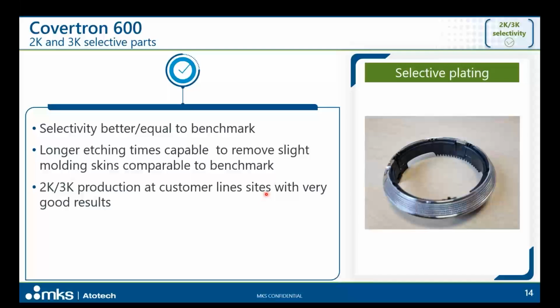Of course, if necessary, longer etching times will be capable of removing any slight molding skins that could be on the surface of the part, and this is comparable to the sulfuric-chromic etching. We confirm this because currently our customers are in production with 2K and 3K parts with very good results. So this is confirmed by production. Here you can see an example of selective plating with our Covertron process.